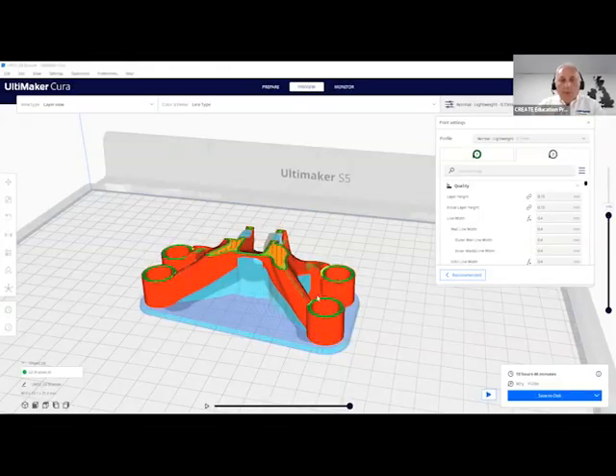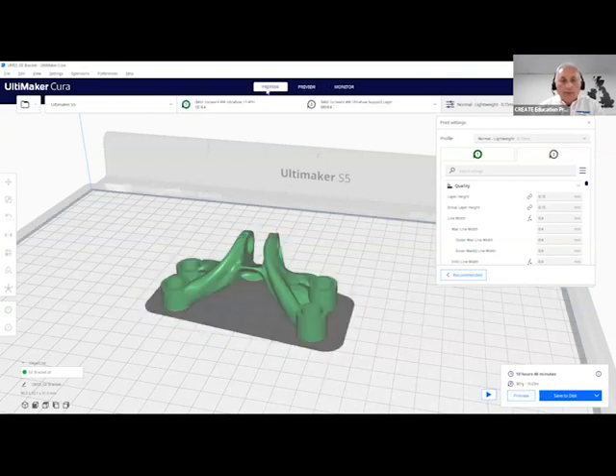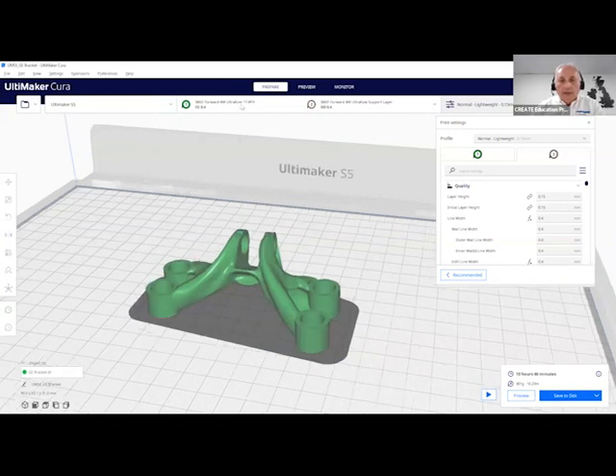So when you bring the part into Cura, you go through your normal import the part, and you need to set the material for both nozzles. In this case, we've got Ultrafuse 17-4 PH stainless steel in one with a CC 0.4 print core, and in the second print core we've got the support layer ceramic material with its own dedicated DD 0.4 nozzle setup.